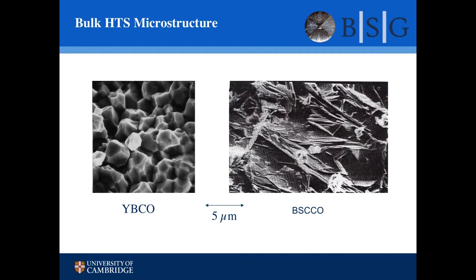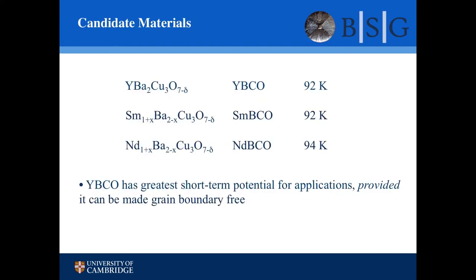The BSCCO materials tend not to be granular, but are very sensitive to applied field. Not so good if you're trying to generate a field. YBCO, yttrium barium copper oxide, the rare earth barium copper oxides, are more granular, but are not sensitive to the applied field. So it turns out the candidate materials for generating high fields, and these are fields compared to the field you can do with permanent magnets, are yttrium barium copper oxide, samarium barium copper oxide, and neodymium barium copper oxide. And there's a relatively new material based on gadolinium that shows even more potential.